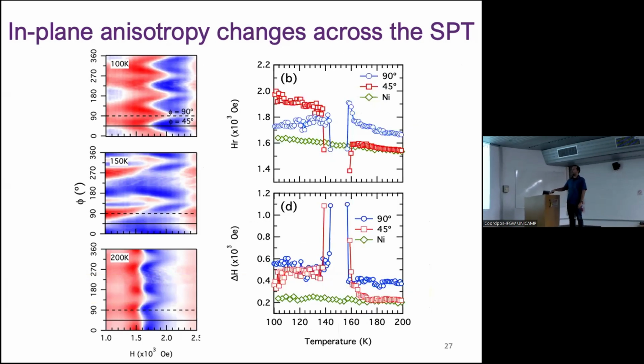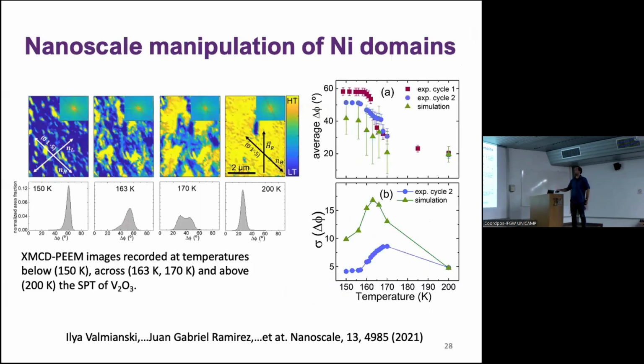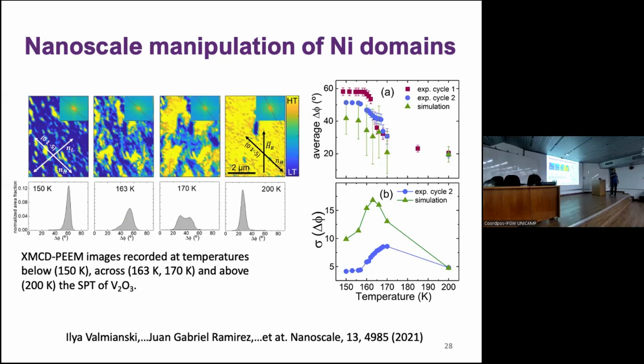And we proved that it actually was a local effect by doing, let me jump into this because I will not have time, some XMCD-PEEM images. So we look into the domains, and then these are the domains. The yellow here is high temperature. The blue color here is the low temperature. And then you see that there are some domains, okay?